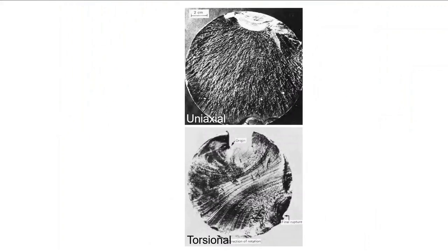Cracks will initiate, grow, and then once a critical size is achieved, it will cause the crack to envelop the entire cross-section of a component. From the features on these two fracture surfaces, it can be seen that there are features that show where the cracks initiate and then propagate at different rates. The type of loading will dictate the morphology features, but it's clear that the crack will propagate at different rates.